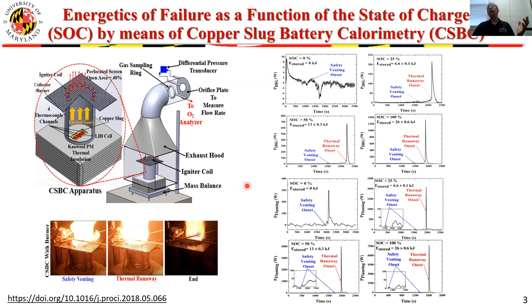And then you do a few calibration experiments and do a little bit of math. From the temperature evolution of the cell that occurs as you provide heating to the system, you can actually infer how much heat is being generated in the cell casing itself during the thermal runaway process. Examples of the traces of the power of heat generation inside the cell are shown here on the right-hand side, and you can see that we can observe this as a function of the state of charge, and you can see the sharp peaks that indicate thermal runaway. Now, if you integrate those sharp peaks, you get the total energy released inside the cell.